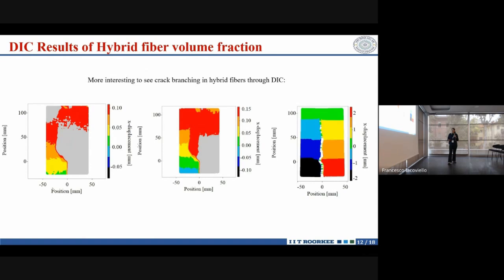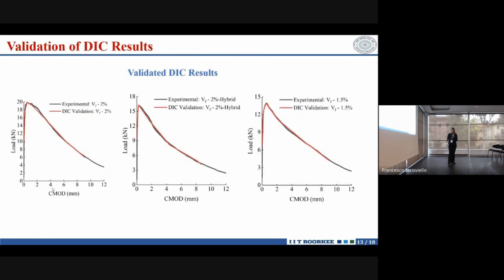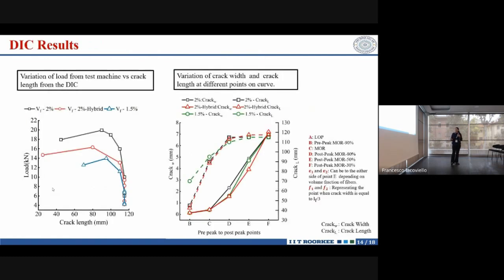So, the results of hybrid fiber volume are also interesting to see, as we can see the crack branching in this. Initially, in the starting stage, the crack was propagating from here, but toward the peak, it started propagating from this, and finally it branched and then went into the common crack propagation. So the DIC results are also in good correlation with the experimental. We have done the validation as well.